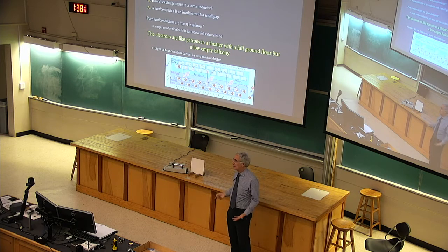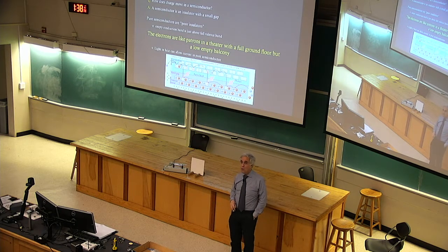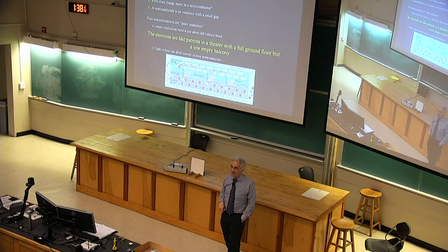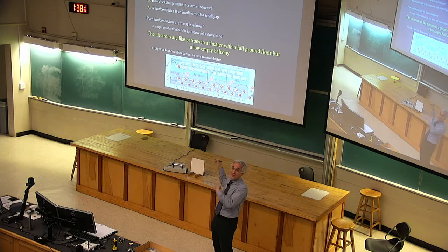It depends on how much light. A little light, you get a little conductivity. A lot of light, you get a lot of conductivity. It's a photoconductor. And we talked about photoconductors back in the days of Xerox machines. Remember that, how Xerox copiers worked? And I said, oh, we'll eventually circle back to how a photoconductor works. This is how a photoconductor works.